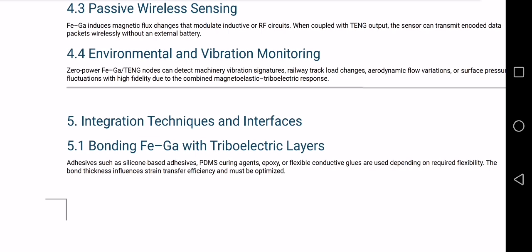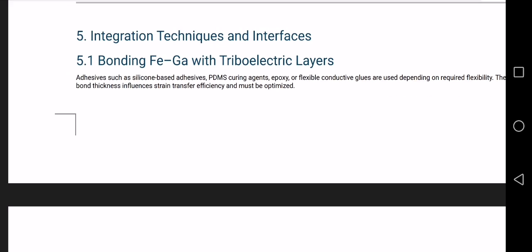Number 5, we have integration techniques and interfaces. Bonding Fe-Ga with triboelectric layers. Bonding materials include silicone adhesives, PDMS, epoxy, and conductive glues. Bond thickness controls strain transfer and must be optimized.